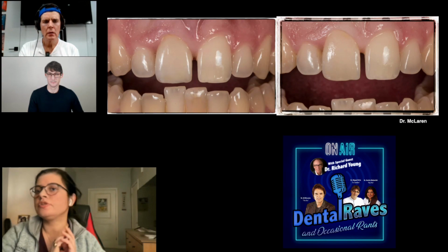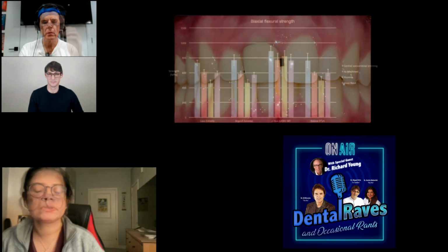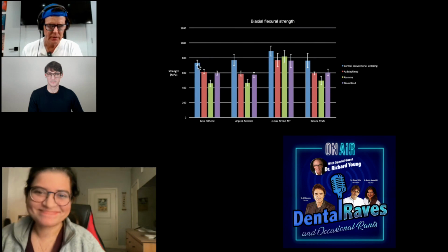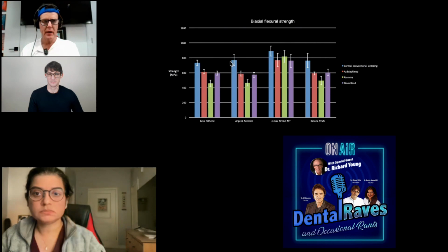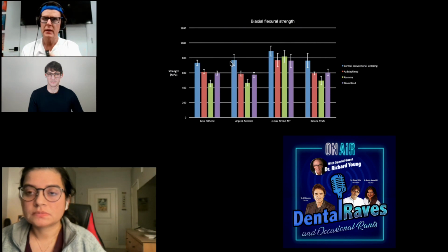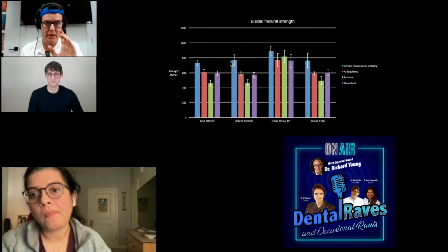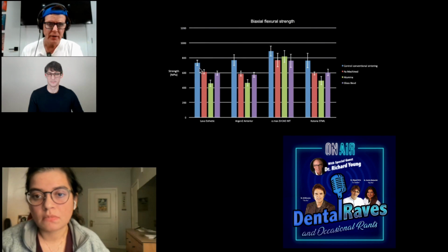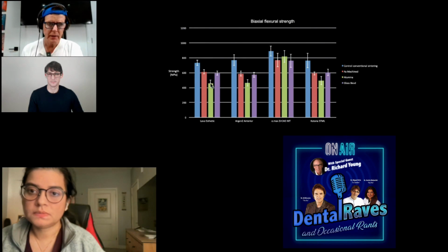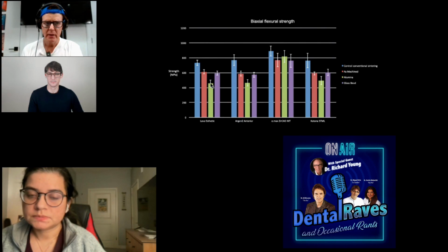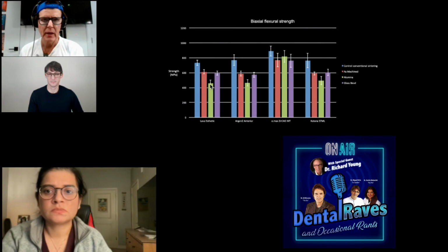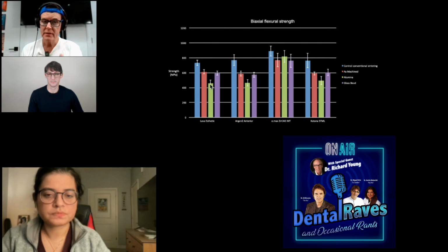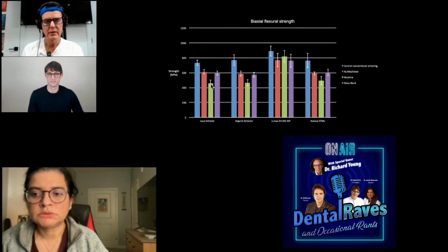Dr. McLaren, if you can show the next slide, that's the pre-op. A quick look at this. What I want to show you, though, is the important point: these companies that say they're 750 megapascals, the 5Ys, the STML, the Argen HT, several out there, you need to know this, because the pure 5Y means 5 mol% yttria. If you sandblast it, you lose roughly 40% of the strength, so you're down maybe around 450 megapascals. For a single crown, that's fine, but not for a bridge. And if you have a thin crown, maybe 8/10 or 6/10 occlusally, you should definitely bond it.